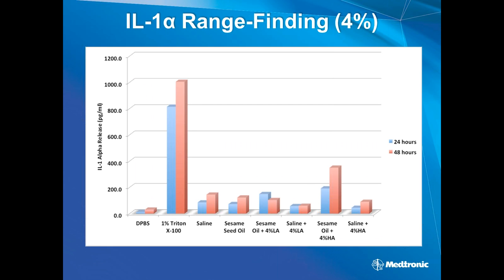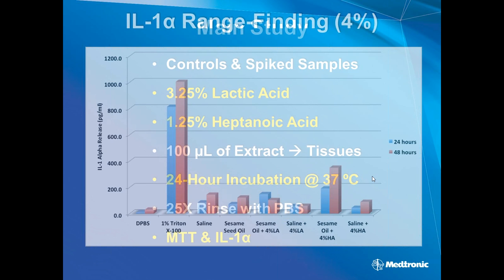But if we look over here on our positive control, we just see that we have a great deal of IL-1 alpha that's being released by this Triton X-100, which is a pretty good irritant. Here, the phosphate buffered saline, we're not seeing much. Our regular saline, we're seeing a little, sesame oil, not too much here, and then we're seeing more of it with the heptanoic acid. So let's keep going here.